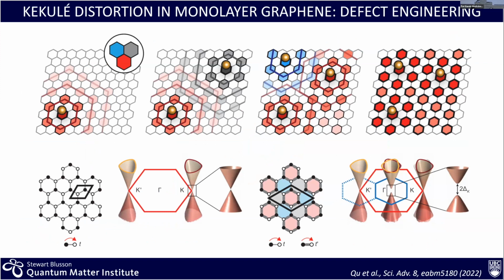Immediately you get into a situation of Friedel oscillation induced by the lithium adatom. Now a second lithium adatom could come in and end up on a different location, which is not in phase with the first one. However, if the deposition is low enough, and the temperature is high enough to allow for some kinetics on that surface, then the second impurity would also align itself in phase with the previous one.